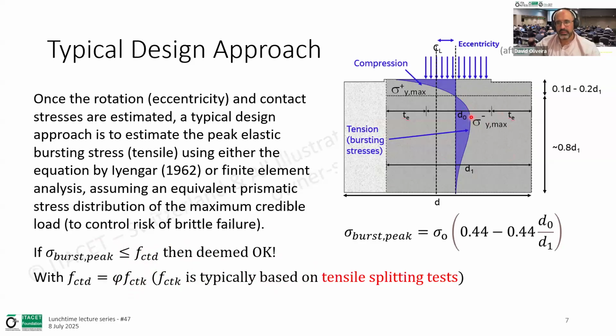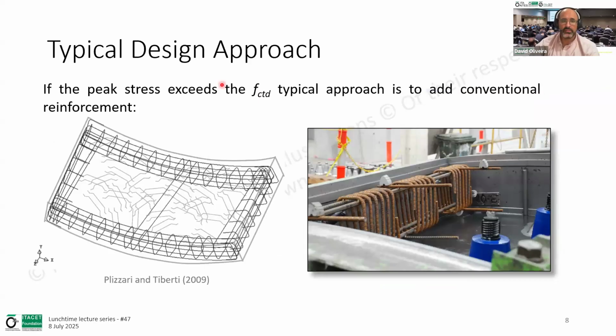If this maximum or peak tensile stress here is less than that capacity, the design capacity, then we generally deem it okay, and we do not introduce additional reinforcement for the joints. We just use the reinforcement that's required for the overall performance of the segments, either with conventional reinforcement or fibers. If the peak stress does exceed the tensile capacity of the concrete, one of the most common approaches is to generally introduce at least some local joint reinforcement, which you can see here in these pictures, by this sketch here and a photo on the right-hand side.